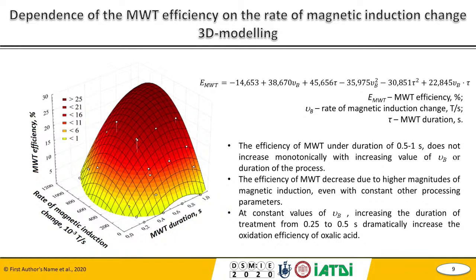The efficiency of magnetic water treatment decreased due to higher magnitudes of magnetic induction, even with constant other processing factors. It indicates the complexity of the relationship between efficiency of magnetic treatment and magnitude of magnetic induction. The efficiency of magnetic water treatment also does not increase monotonically with increasing duration of the process. Thus, at constant values of magnetic induction change, increasing the duration of treatment from 0.25 to 0.5 seconds dramatically increases the oxidation efficiency of oxalic acid.